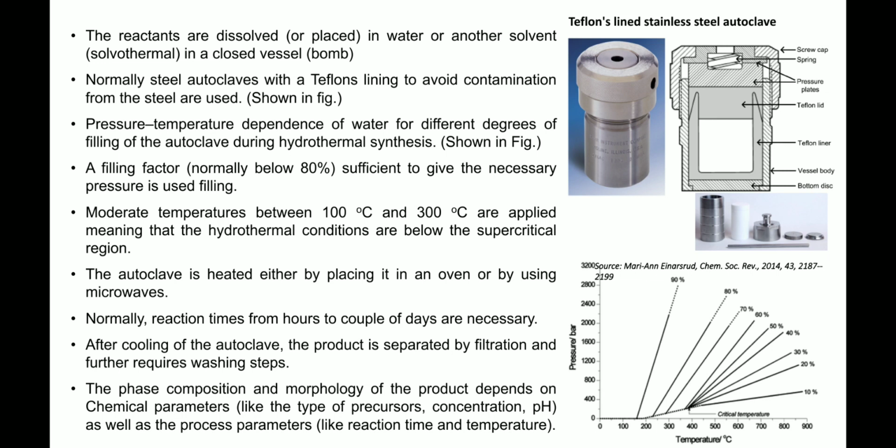There is no generation of pressure, because you have fully filled that Teflon liner, and there is no space for the generation of pressure. So that's why a filling factor which is normally below 80%, below 90% is important, to fill below 80 or 90% of the volume. Okay, so a filling factor normally below 80% is sufficient to give the necessary pressure.